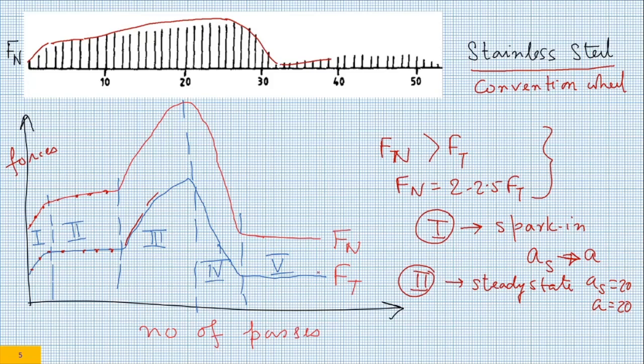In the third phase, what is happening? In the third phase, the wheel loading is taking place. So possibly a grit has lodged itself and reduced the intergrit space, so the forces have gone up.